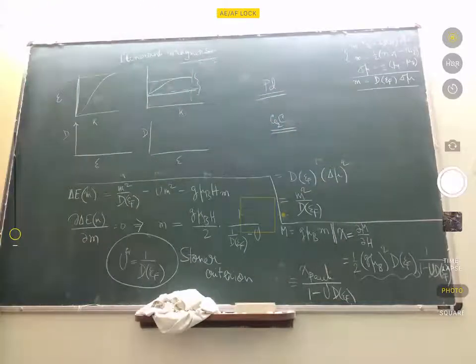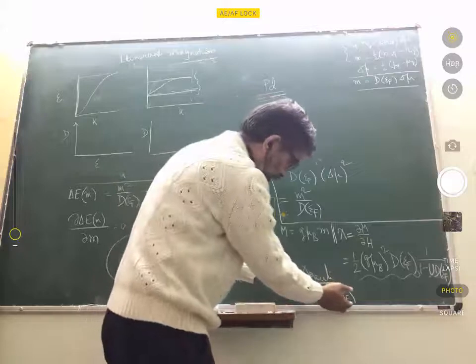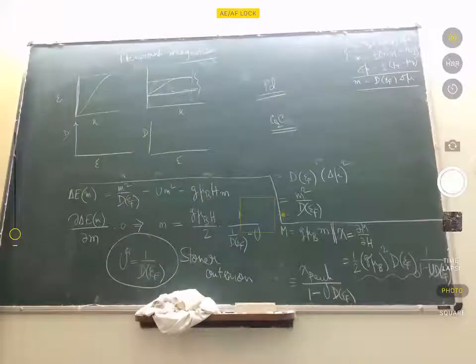Palladium is a metal, of course, and it happens to have a large density of states at the Fermi energy. I'll try to show you a plot of density of states for palladium. So it's not a ferromagnet. Bulk palladium is not a ferromagnet, but because of the fact that the density of states is large near the Fermi energy, this denominator is pretty close to 0. Sorry, it's not 1, it's pretty close to 0.